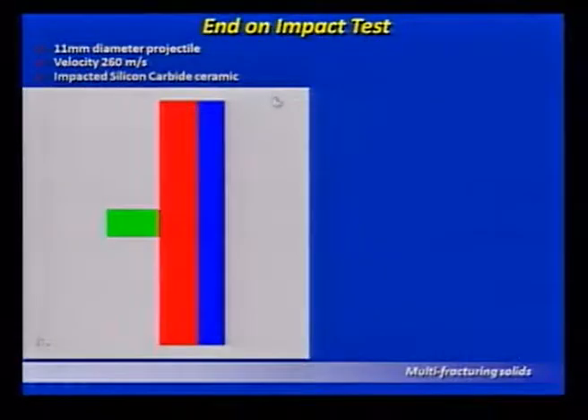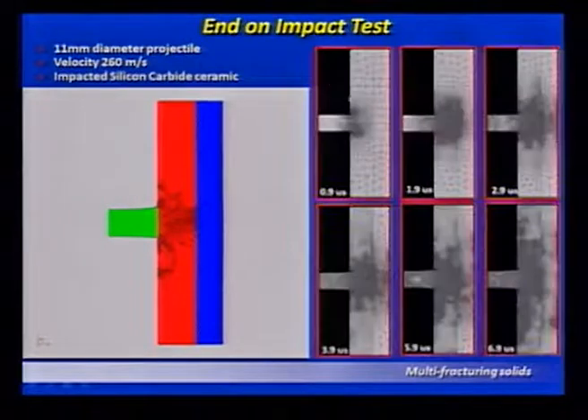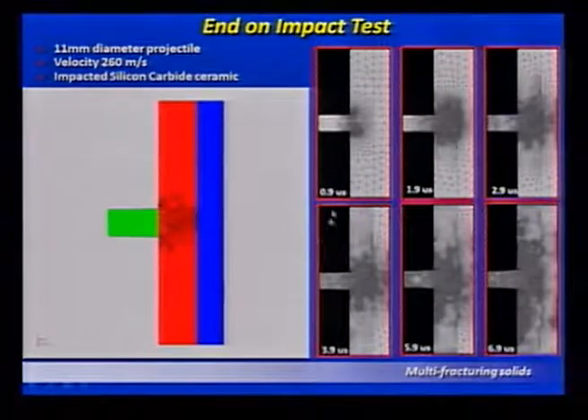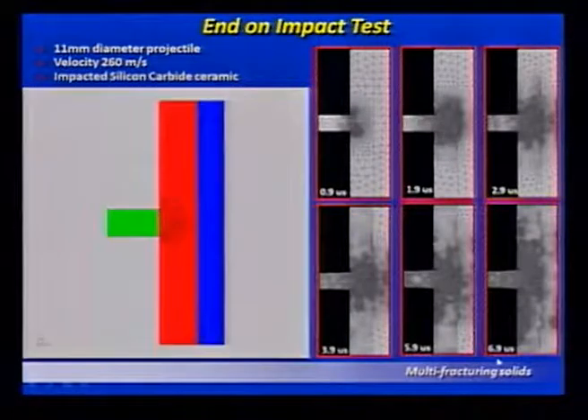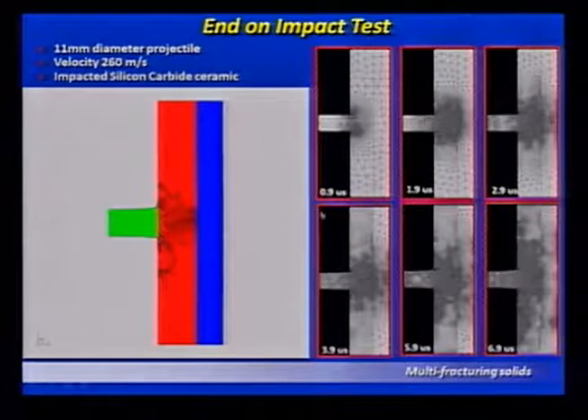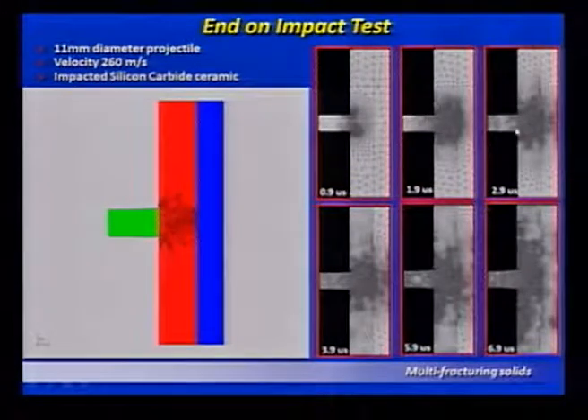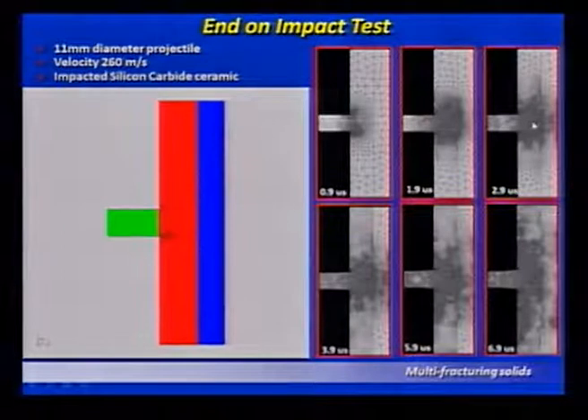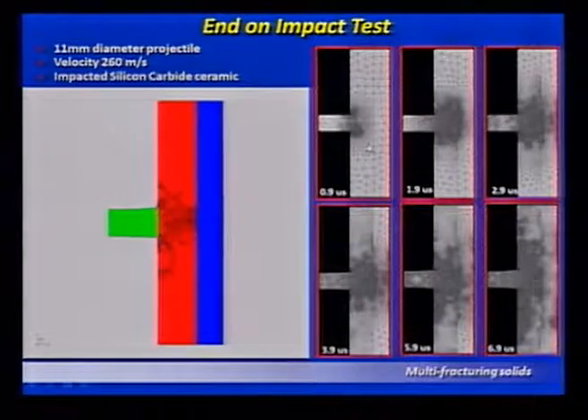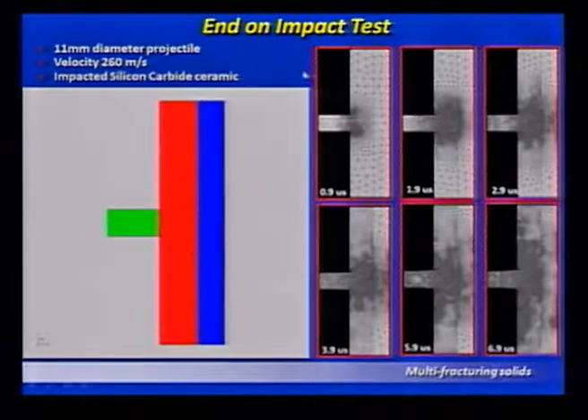is correct, is validated. This is the so-called end-on impact test, which is a silicon carbide ceramic. This is a tungsten impactor, steel plate. If you impact it, you find that you develop fracture patterns like that. The reason I want to show this is that you need to continually remesh this problem. As you go from 0.9 microseconds to 6.9, you see the fractures developing, and that means we have to continually update the mesh so that we can model the individual fractures. So we go from a very coarse mesh to a very fine mesh, and this is done by automatic remeshing.